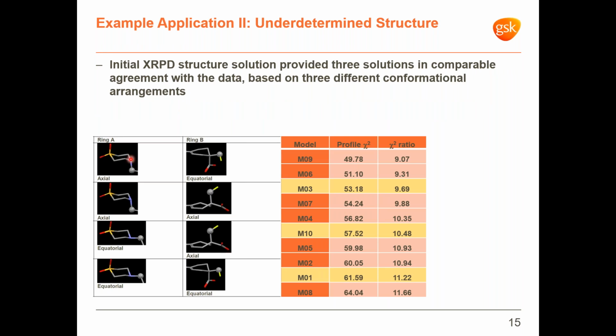So from the initial XRPD structure solution step, we obtained 10 candidate models reported in this table in relation to the 10 possible conformer combinations. And from these, three truly unique ones were identified based on supramolecular environments of the hydrogen bonding functions. Of these three, M03 has one independent molecule with both ring A and ring B axial, and the other with ring A equatorial and ring B axial. On the other hand, solution M10 has both independent molecules with ring A equatorial and ring B axial. And finally, the M01 solution has both independent molecules with both ring A and ring B axial. And at this stage, it was not possible to discriminate among these three solutions based on XRPD only.